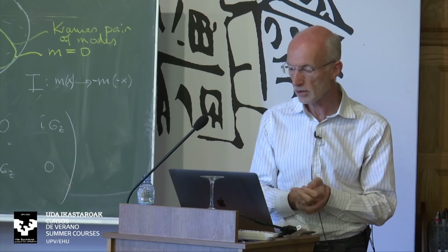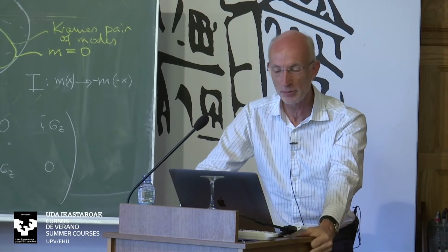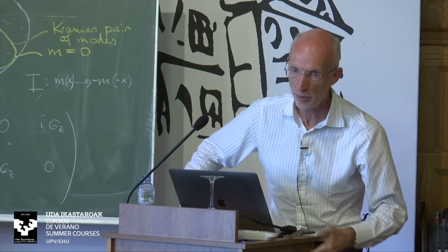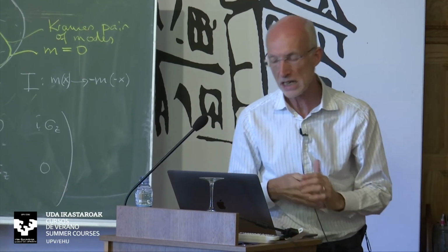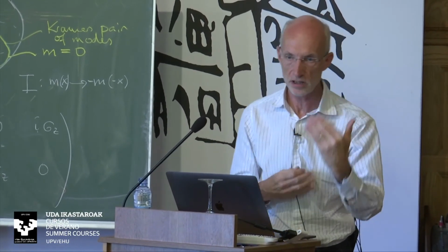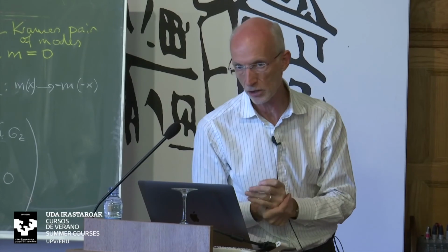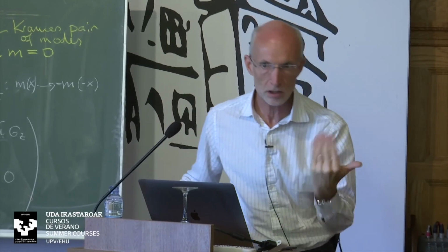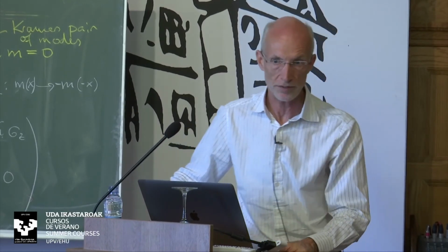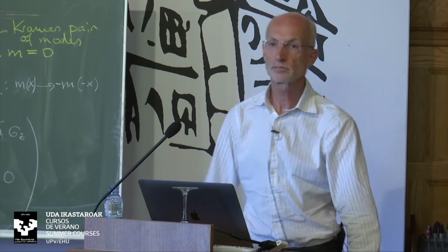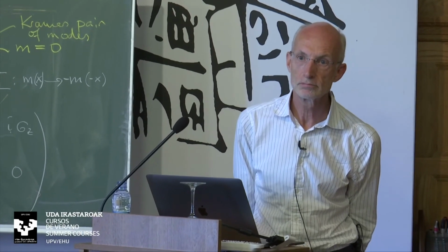You may be thinking that the line edge roughness will play a role in pinning the domain walls. It turns out that's true for conventional spin transfer torques. But these types of torques, which I will get to in the next foil or two, can actually overcome very significant pinning potentials compared to conventional torques because they have very large field-like contributions. And so we seem to be very insensitive to things like edge roughness or defects, which is quite a surprise. And do you have one sputtering device which can sputter all these different metals?